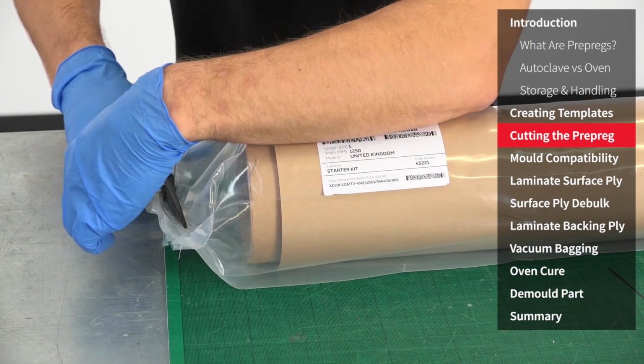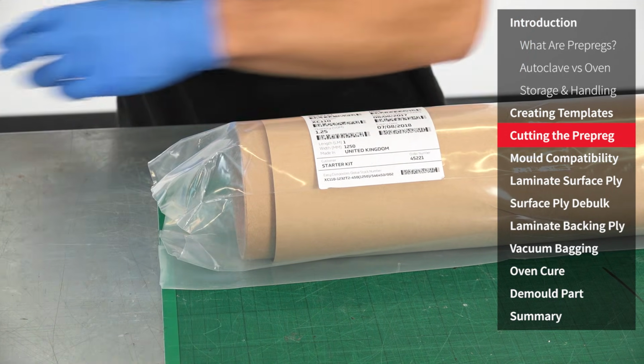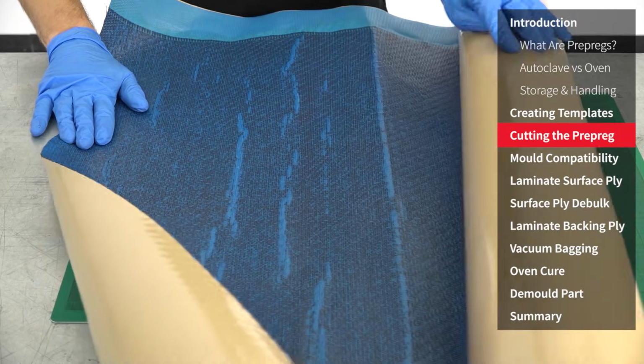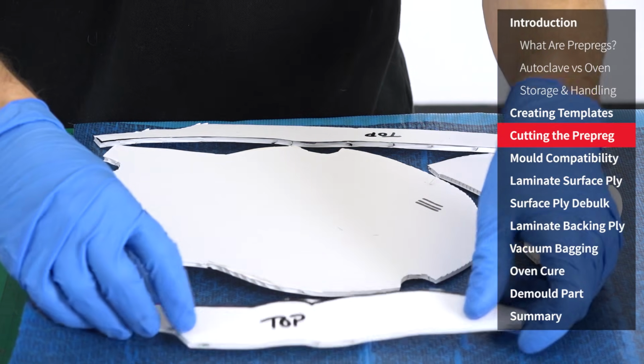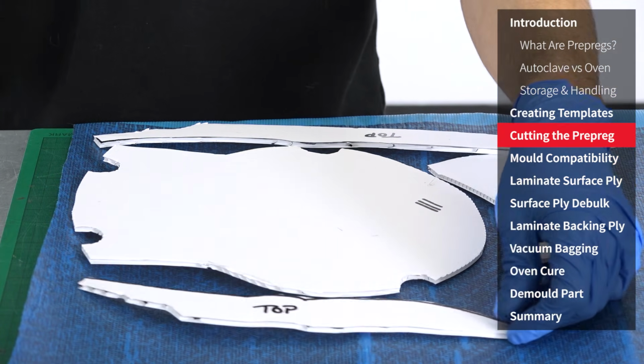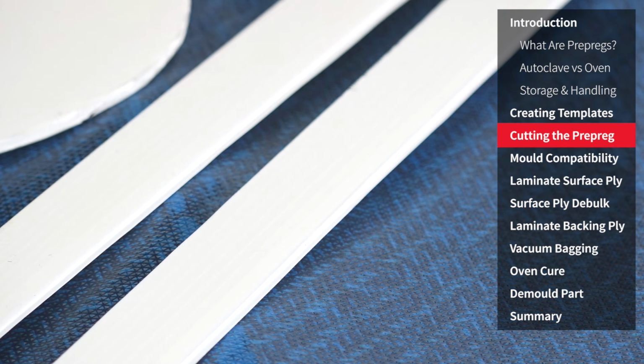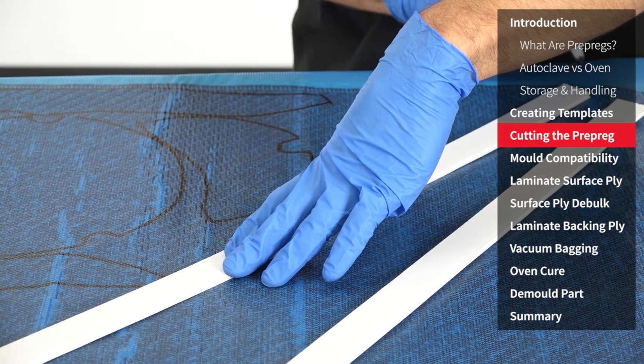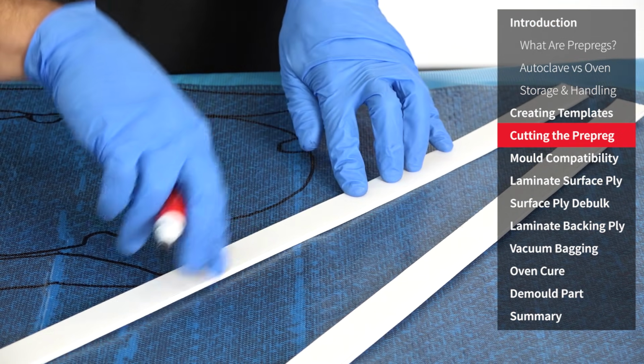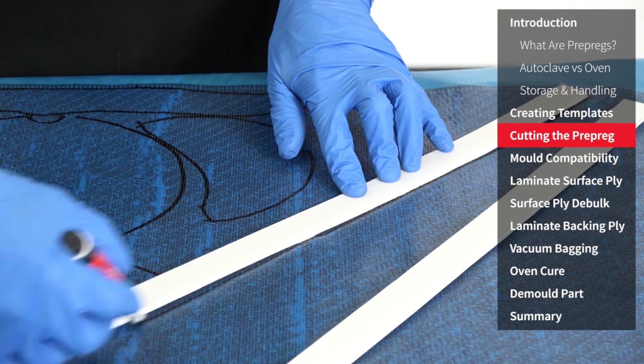The backing ply can now be removed from its packaging and templated and cut in just the same way as we did with the surface ply. This is a heavier 450 GSM carbon, as opposed to the 210 GSM that we used in the surface ply. This builds the thickness more quickly and cost effectively than using the 210 gram throughout.